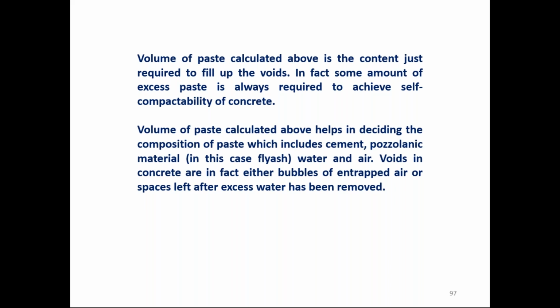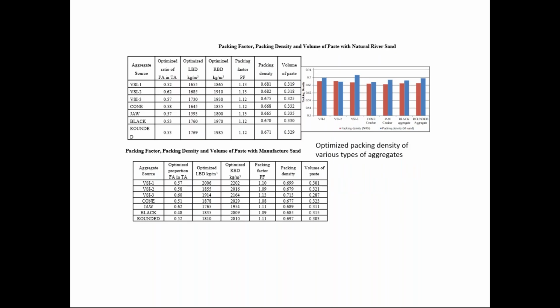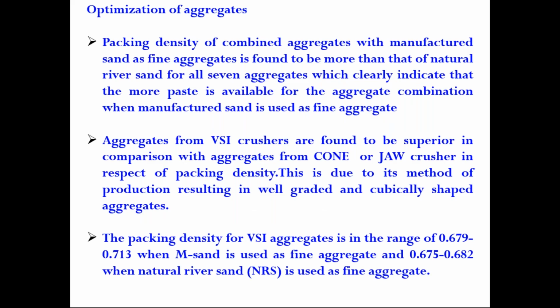Volume of paste calculated above helps in deciding the composition of paste, which includes cement, the cementitious material, which can be fly ash or GGBS, and water and air. Voids in the concrete are in fact either bubbles of entrapped air or spaces left after excess water has been removed. So like this, you can find out the various parameters of bulk density and packing density. So what is the essence of this optimization of aggregates? Packing density of combined aggregate with manufactured sand as fine aggregate is found to be more than with natural river sand for all the aggregates tested, and this indicates that more paste is available for the aggregate combination when manufactured sand is used as fine aggregate.